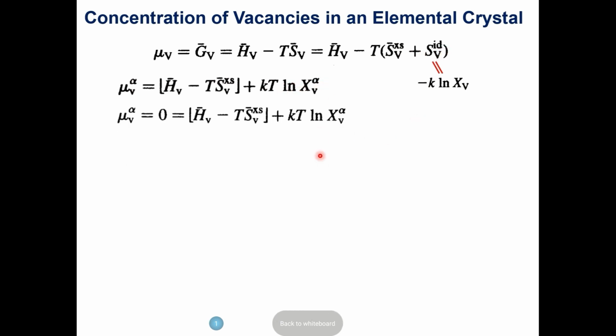And we already know that if you create the equilibrium amount of vacancy, the second law of thermodynamics says that the chemical potential of the vacancy has to be equal to zero. There's no other option—this is why I stress that level first. So that's what's important: that potential is zero, so you can set this equal to zero, and you can actually solve for this fractional concentration of vacancy in the solid.